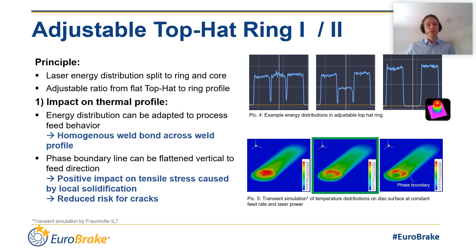Another effect of the thermal modulation can be seen in the phase boundary — a small thin black line visible in the pictures. The phase boundary indicates the solidification behavior and also the melting behavior of the metal before and after coating. In general, the heating and cooling of the material before and after the process cause stress. The way of solidification after the process has an impact on this effect. The more even the solidification happens, the less stress is caused by the temperature impact. As a result, optimizing this line reduces the risk of cracks due to stress in the coated layers.